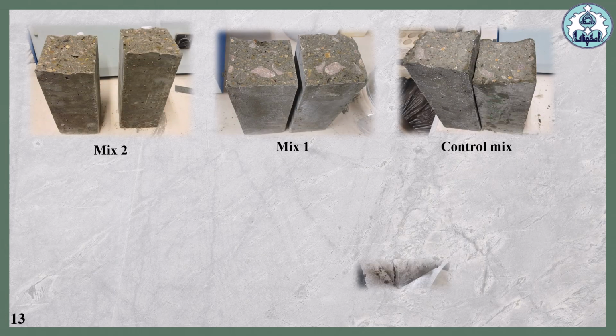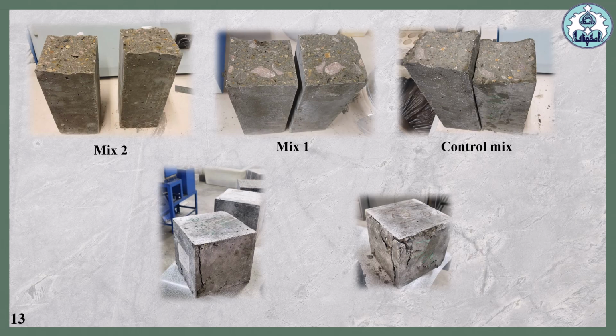The slide shows the failed concrete specimens after mechanical testing. Images of compressive and flexural test samples are presented for all 3 mixes, including the control mix and the slag cement-based mixes. The failure patterns provide a visual comparison of the behavior of different concrete mixes under loading.